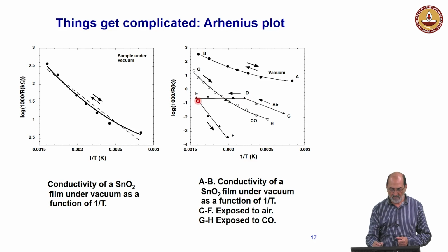Eventually at some point we decided to go back with temperature, and it obviously goes through a completely different path. So something happened in between, and what we think happened is that the air diffused into the grains and then the conductivity is lower. Well, that is my interpretation. As I told you, many don't think this is going on. I don't know how they explain this.